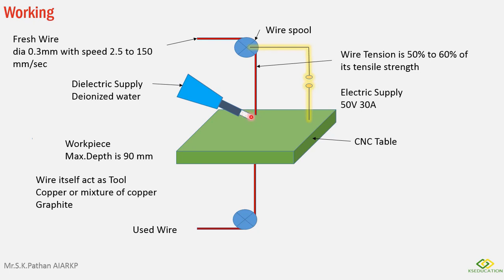this dielectric fluid goes from non-conductive to electrically conductive, and as soon as this dielectric fluid becomes electrically conductive, a potential difference is created between negative and positive, and because of that there is a spark, and this spark is responsible for melting the metal. So here the actual machining is, because of the increase in heat, material is softened, and when the electrical spark is discharged on that soft material, it is removed.